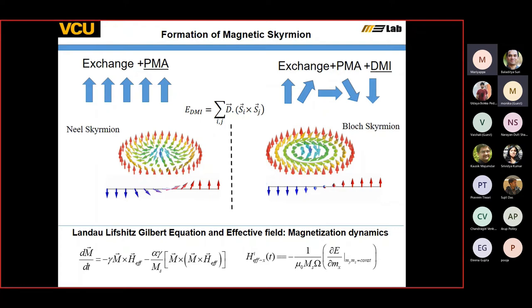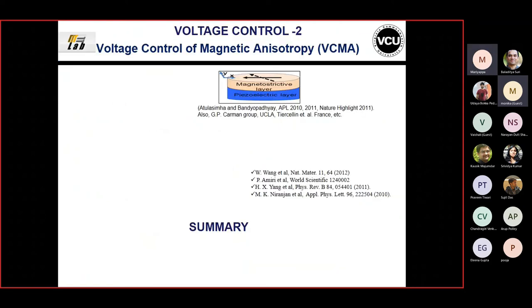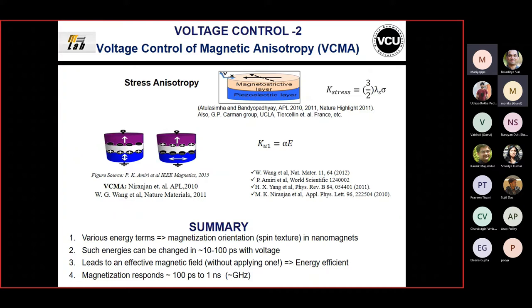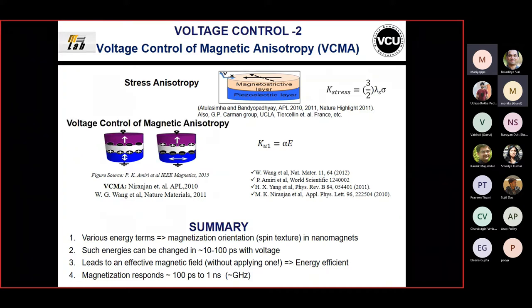We model all the dynamics using the Landau-Lifshitz-Gilbert formulation because it's relevant at these scales - for nanoscale magnets, not individual spin dynamics. This has the Larmor precession term and the empirical damping term called the Gilbert damping. The key tools we have to control the magnetic state in our lab are stress anisotropy and voltage control.